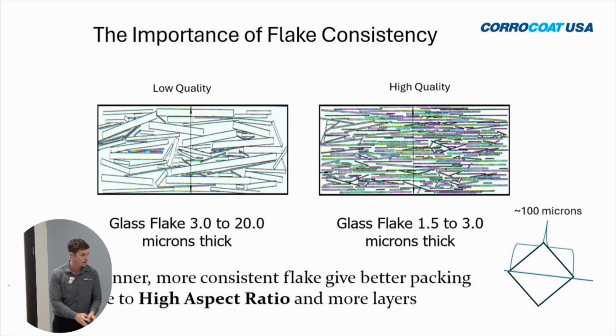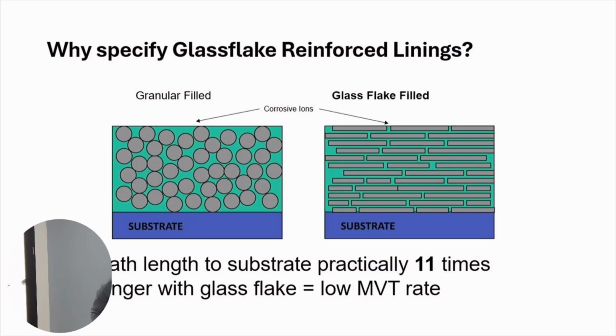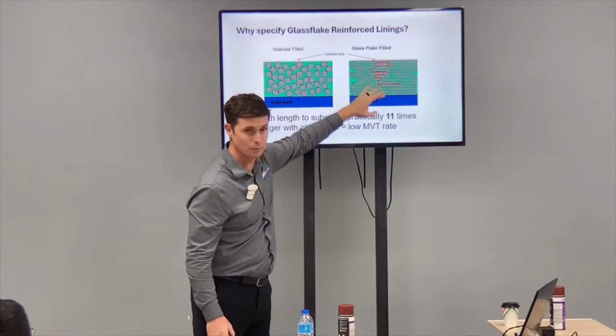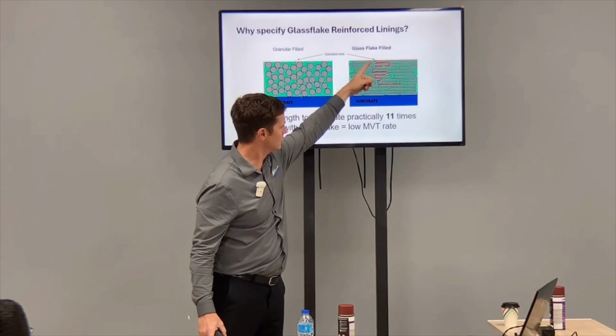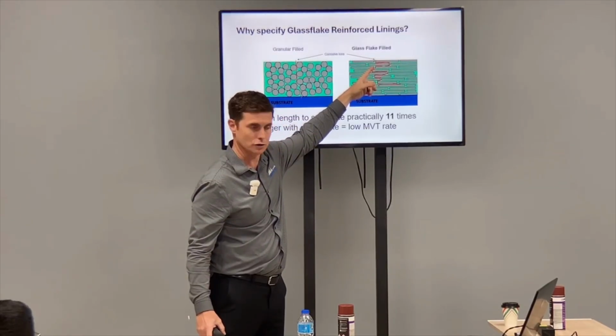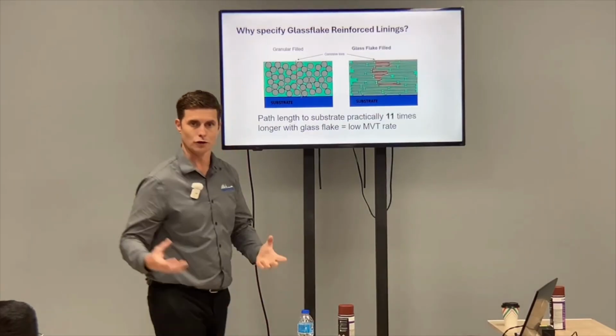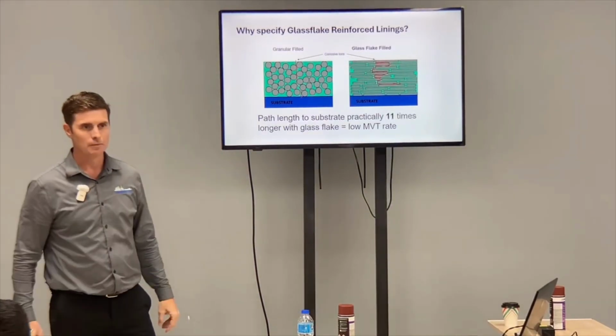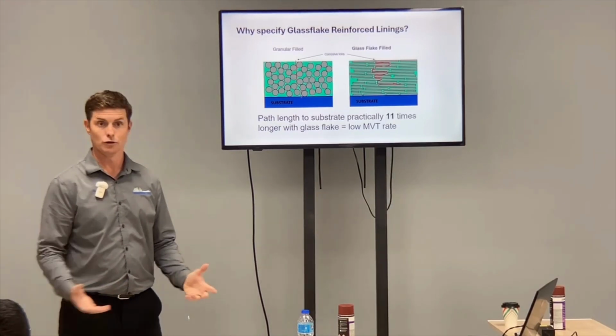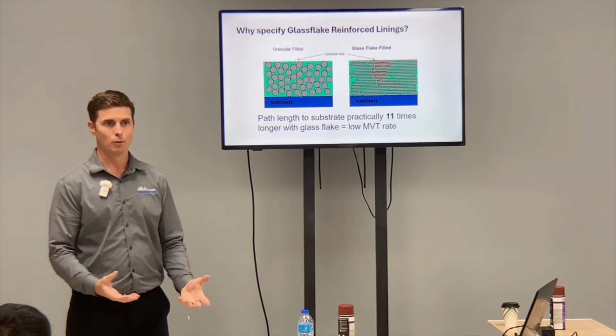The idea with the tortuous path, and this works the same as if you, mouse problems again. So if you don't have a thick enough coating for the given surface, we specify that based on the surface, or if the glass flakes are such that to where they don't give you enough of a path, you're not going to stop the flow of the corrosion-causing ions. They're going to get to the bottom, they're going to start corroding, and you're going to end up with a bubble over a given amount of time. That's the key reason why Corrocoat started making their own glass, is that it's that important.